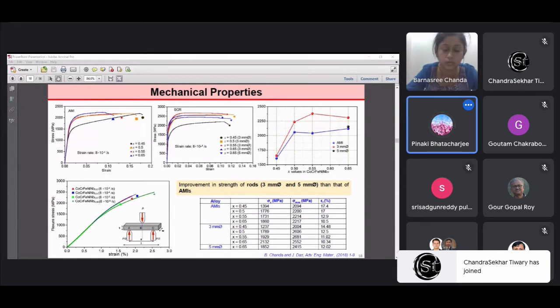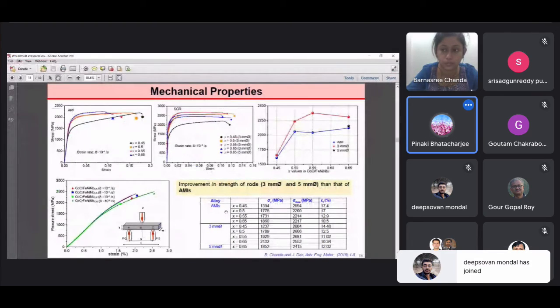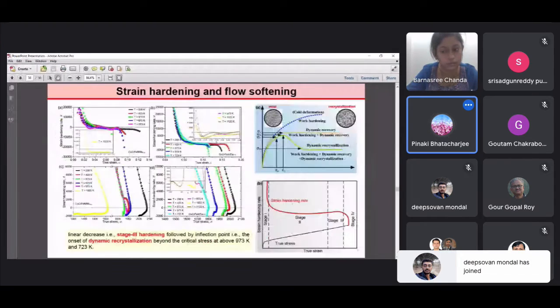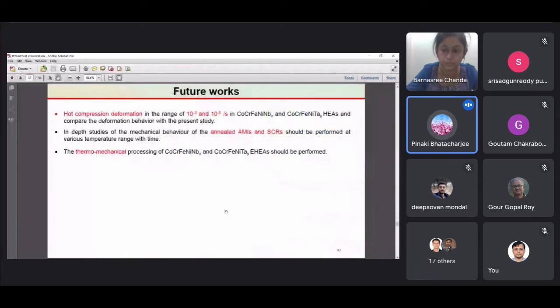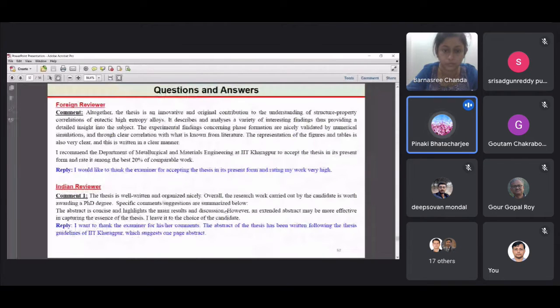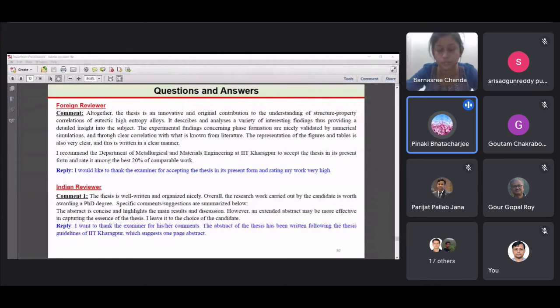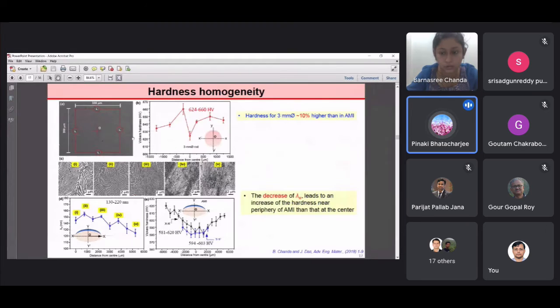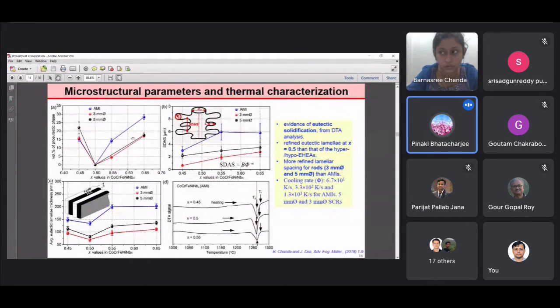Okay. So this is one comment, but this is to give you a broader perspective on this. Now the second comment, and later you can go through my comments, is that in general Laves phase is known to be a brittle phase. Yes, sir. Okay. So you do not expect a lot of tensile ductility. What is typically the fraction for your hyper eutectic composition?